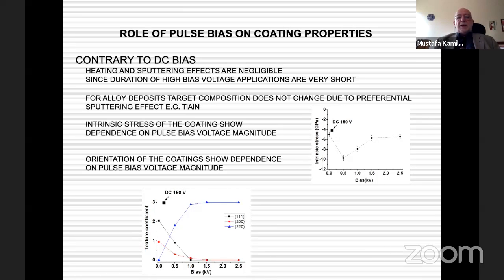So as I said, bias voltage has a dominant role on the properties of the coatings. So when you continuously apply a high voltage bias, as I said before, you end up with a very dramatic increase in substrate temperatures. So the idea was here, why don't we apply a pulse bias? What I mean is that we apply a bias for a microsecond period, and then we make an off period. So in this manner, we can pass the bias voltage, and we can benefit from the positive role of high voltage bias without too much increasing the substrate temperature. And this methodology has been used very extensively in KIPT for the deposition of carbon-based coatings.